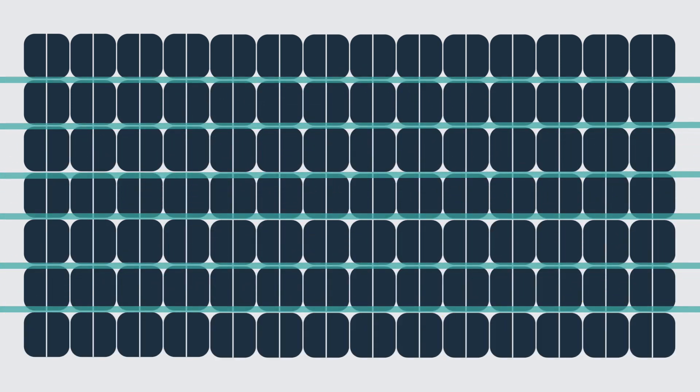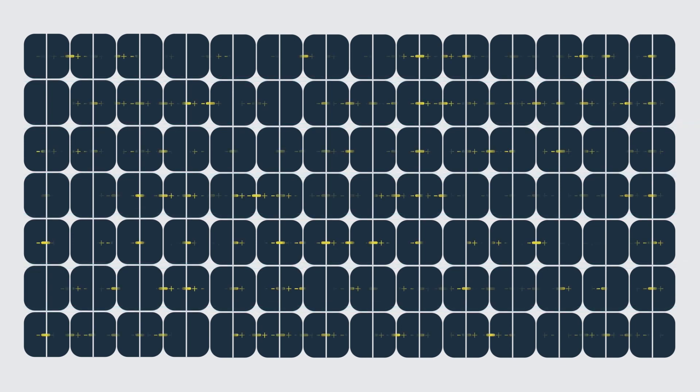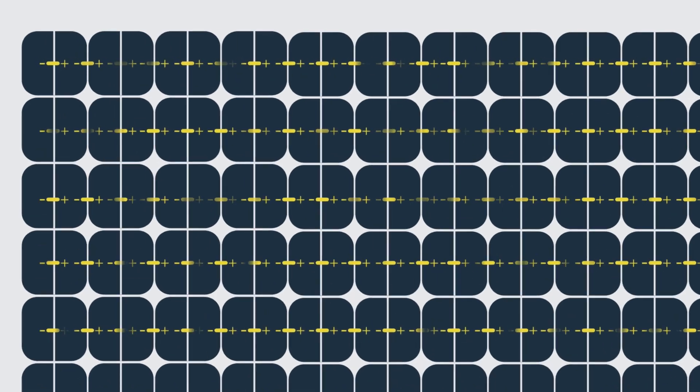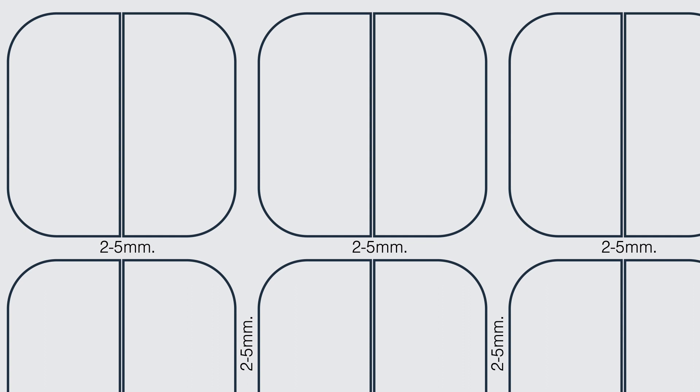In addition, the circuit layout is quickly fixed by means of the dispensing machines. It is worth noting that, in order to ensure the reliability of the solder strip once it is attached above and below the cell surface, a fixed distance of 2 to 5 mm should be maintained between the horizontal and vertical direction of each cell in the assembly.